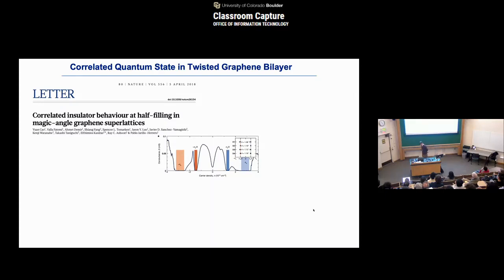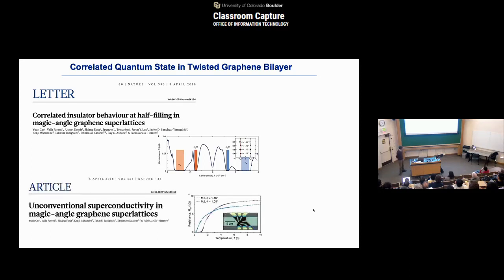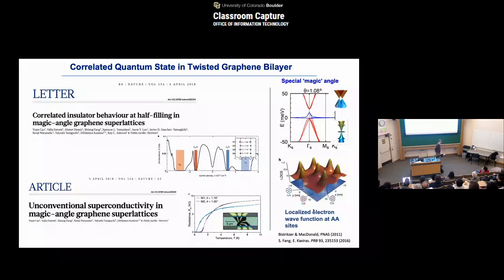Pablo Jarillo-Herrero's group at MIT demonstrated some weird phenomena. What they did is put graphene at the magic angle of 1.1 degrees, and they saw that graphene suddenly turns into an insulator. But then, when they actually dope this insulator, which is not supposed to happen in the single particle picture, graphene turns into a superconductor. And this superconductivity seems deeply tied with the flat band that appears at the so-called magic angle, right? And that basically shook the 2D materials community.